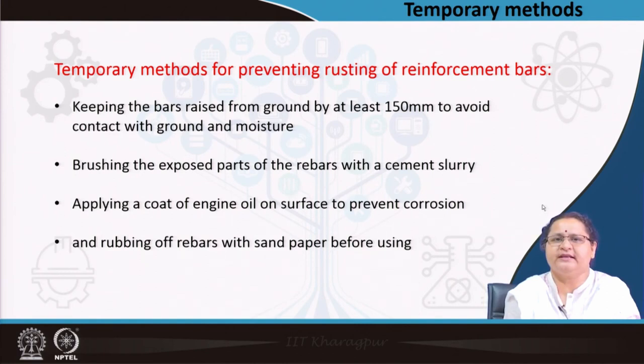You are putting or dabbing cement slurry on top of it. You can also coat it with engine oil on the exposed surface to prevent corrosion. But when you reuse it, you must wipe it off with sandpaper. Otherwise, this engine oil will prevent bonding with the concrete. So, these are the two things which can be done. One is painting with cement slurry, the other is coating with engine oil, but the first one is preferred.